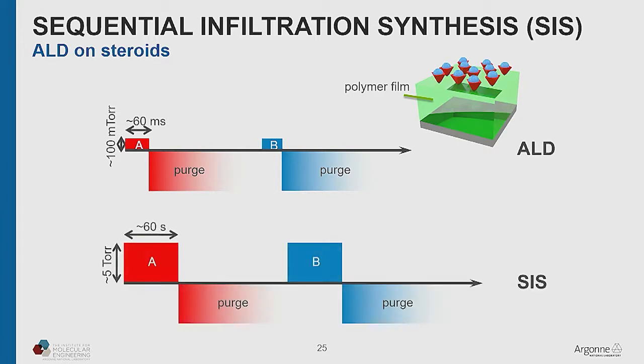But if you operate in a different regime where you increase the pressure by an order of magnitude or more and the time by an order of magnitude or more that the surface is exposed to those vapors, instead of just decorating the surface, it'll have time to diffuse down inside the polymer film. Because remember, these are vapor phase molecules. And if you design your chemistry right, you can have binding sites on the polymer chains that will have an affinity for that first precursor, for the A. And that will allow you to grow bulk inorganic material inside a polymer film.